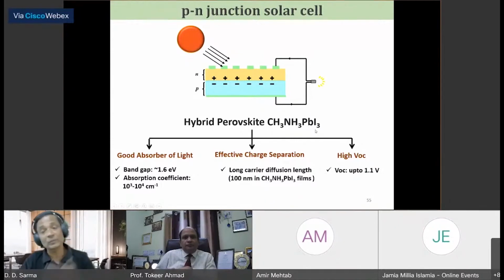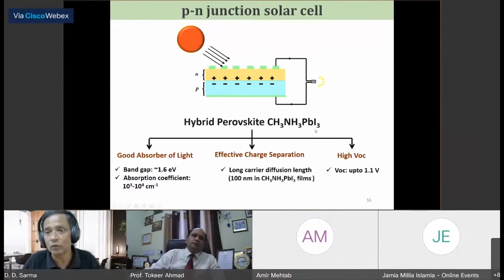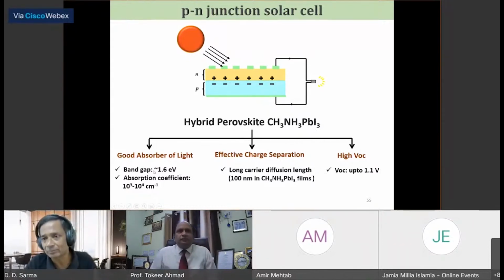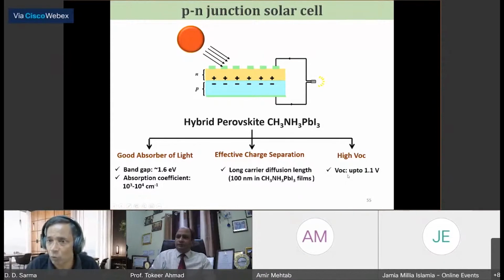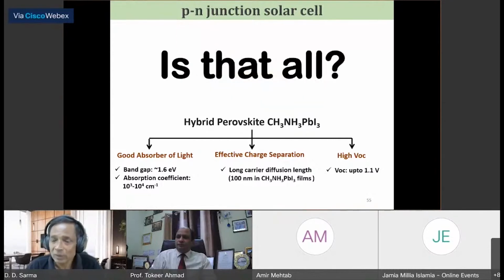This material has been known before, but nobody knew how fantastic it is. It has an almost ideal band gap, a little less than 1.6 eV. It has an extremely high absorption coefficient. It has a very long carrier diffusion length, and a very high open circuit voltage, giving rise to very high power. But is that all? I'll end with this question, because it turns out that it's not all.